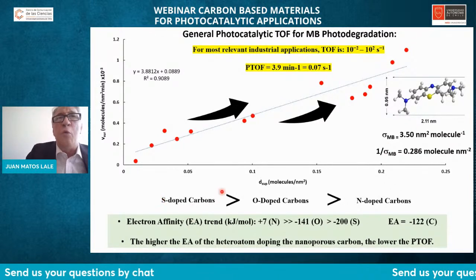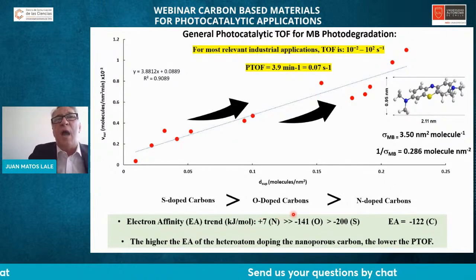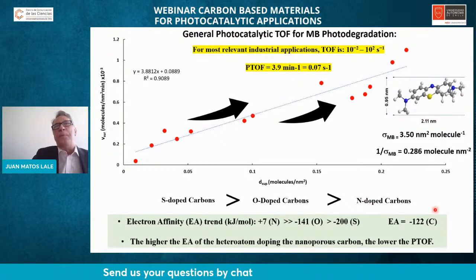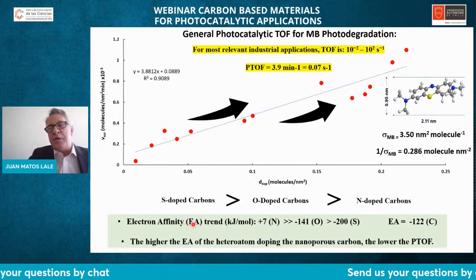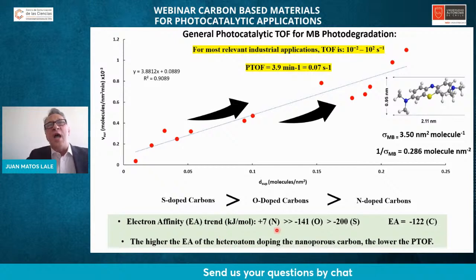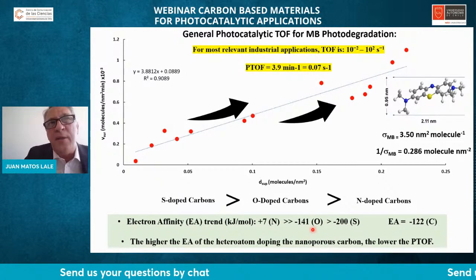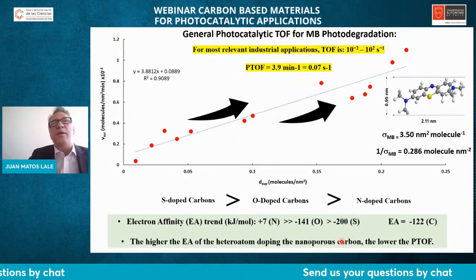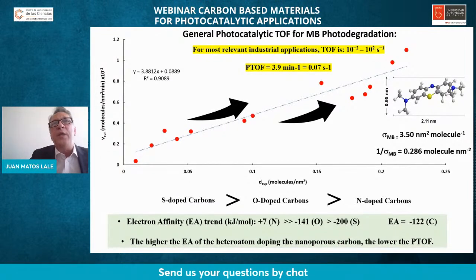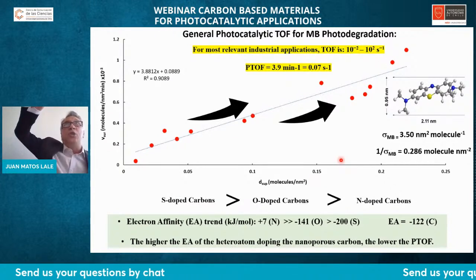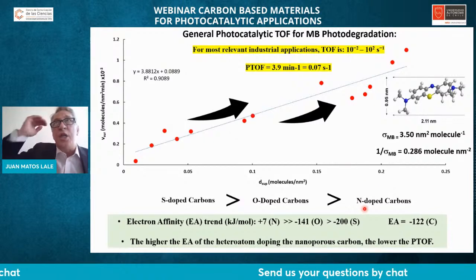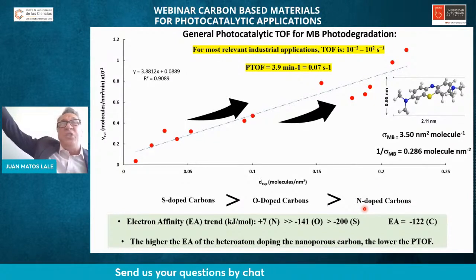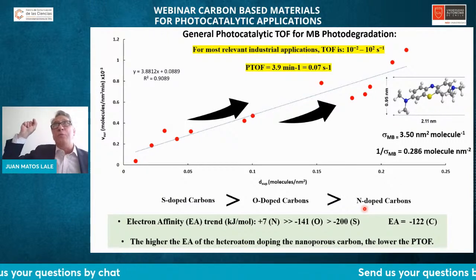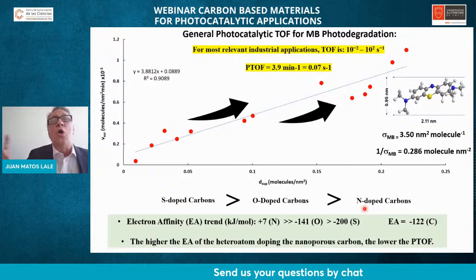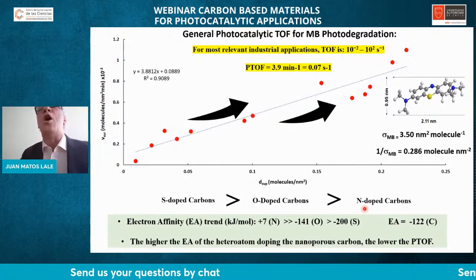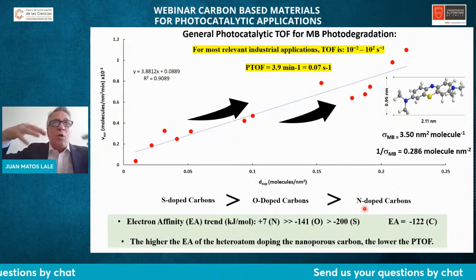And the reason why sulfur-doped carbons are better than oxygen-doped carbon, and these two are much better than nitrogen-doped carbon, is because of the electron affinity. There is nothing new here. The electron affinity of nitrogen is by far much higher in comparison to oxygen or sulfur. That means the higher the electron affinity of the heteroatom, the lower the P-TOF, because if we are dealing with excitation of electrons and you have nitrogen in your system, the electron does not go to the formation of superoxide anion radicals or hydroxyl radicals. It would be captured by the atoms of nitrogen. So nitrogen is fantastic for reduction, but not for oxidation. There is nothing new here, only a correlation of parameters.